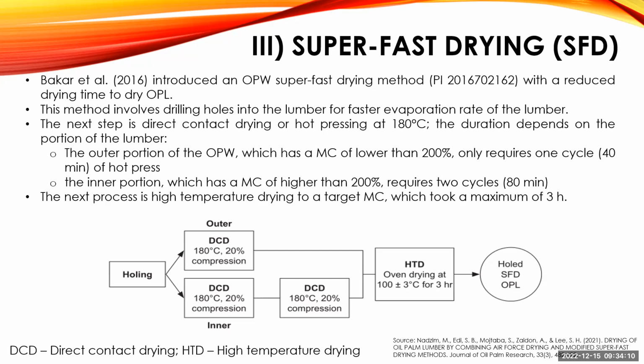It was reported that before drying, we will do some holing in the oil palm lumber, with different hole patterns, and then subject it to direct contact drying using a hot press, applied differently according to different parts of the lumber. For the outer layer of oil palm wood, the temperature used is 180 degrees with a 20% compression applied.